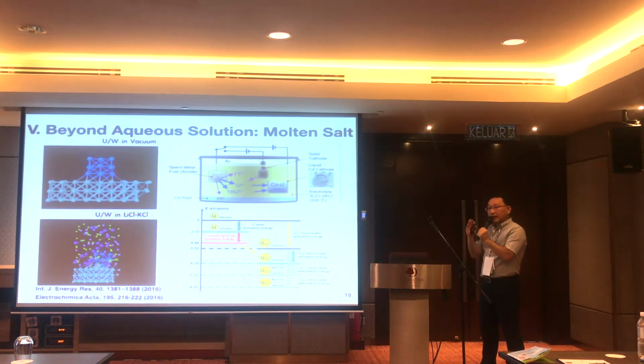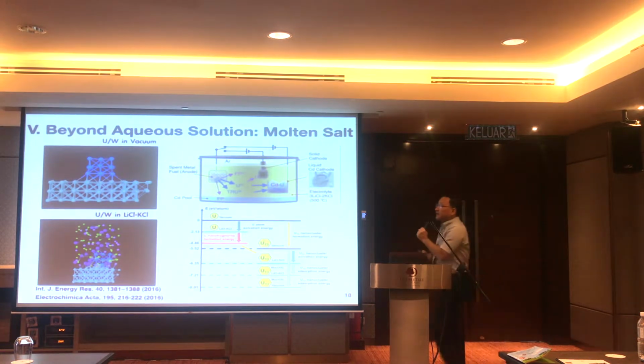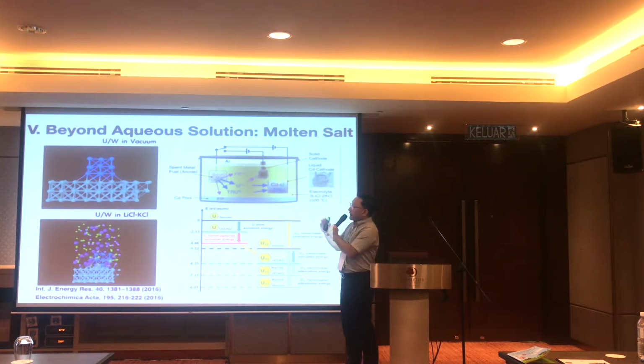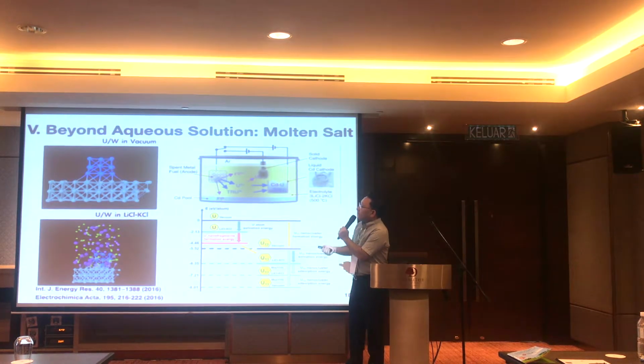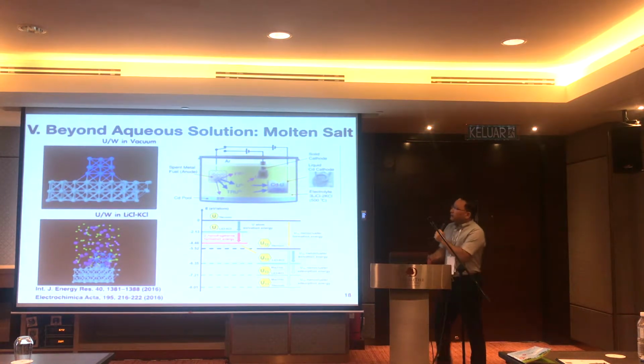Most of the rare earth reservoir is in China now. Right? So we are going to separate the uranium from rare earth materials. We need very good electrode materials to selectively take out only the uranium. We are currently developing a tungsten electrode in molten salt, basically a chloride molten salt, LiCl-KCl molten salt.